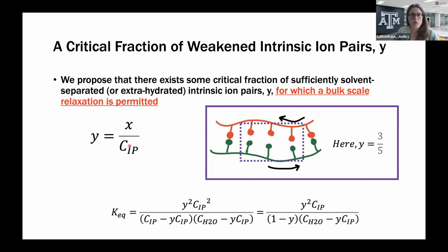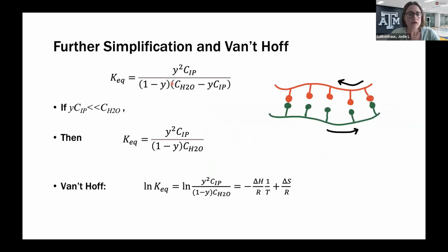So with that parameter, Y, we introduce that into our equilibrium equation here. Okay. And then we make one assumption. We assume that Y times the concentration of intrinsic ion pairs is much less than the concentration of water to get this new relationship. And now we're going to bring in a Van't Hoff type relationship, where we say the natural log of our equilibrium constant is related to an enthalpy and an entropy here.